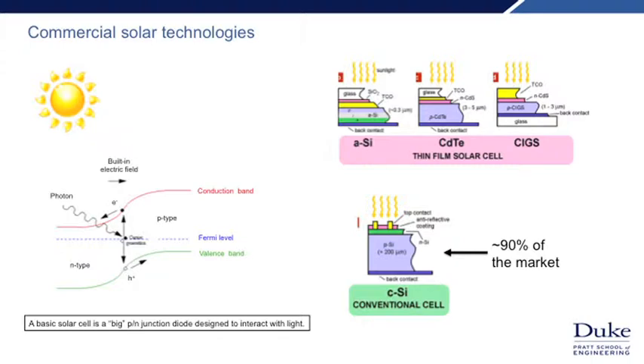There's a second class of solar cells known as thin film solar cells, which employ much more effective materials for absorbing sunlight — things like cadmium telluride, or CIGS, which is copper indium gallium sulfide selenide. In these cases we can get by with on the order of a micron, or maybe up to five microns of material — about two orders of magnitude less material than in silicon-based devices. The idea behind thin film devices is that by using much less material, we can hopefully save costs.